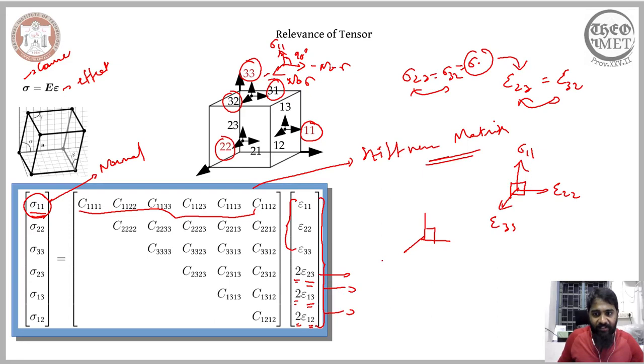But on the other hand, if these thetas that I'm considering are not equal to 90 degrees, then in such a case, I will be able to resolve my normal stresses to also the shear stresses that act on the plane. So if I have a crystal system wherein the crystallographic angle of the system is not orthogonal, it's not 90 degrees, then it becomes possible for me to have shear components of stresses even though all that I'm imposing is the normal load. So only in those cases, this makes absolute sense.